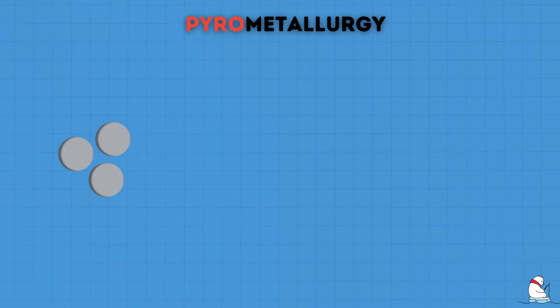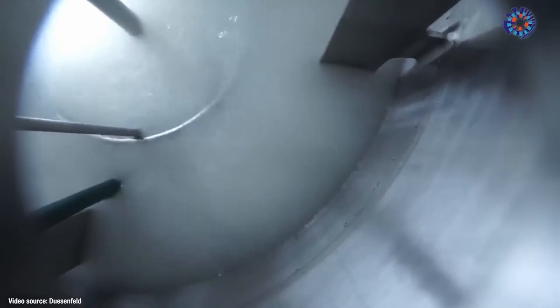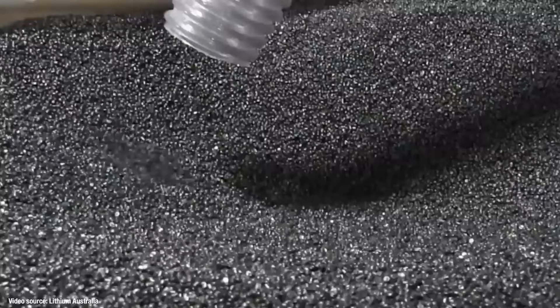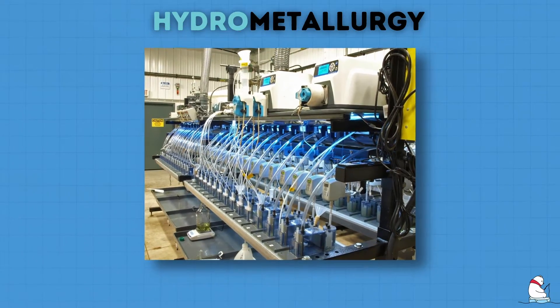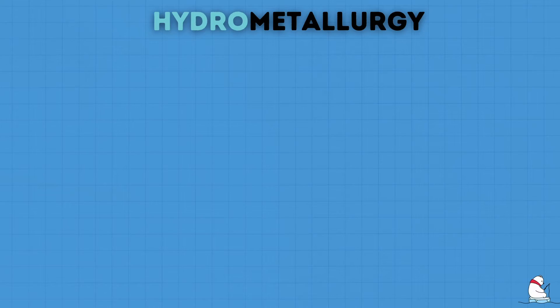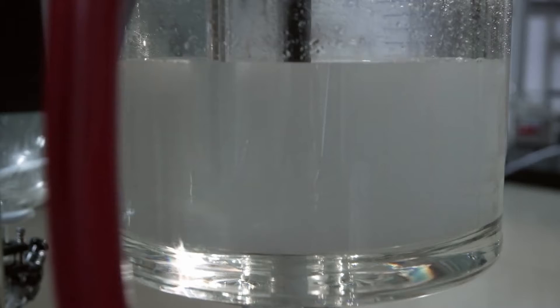The alloy with the other more valuable metals then goes through a hydrometallurgical process. This includes acid leaching and multi-step precipitation to get battery-grade salts of cobalt and nickel. These metals tend to be the focus due to their higher price and thus value. The other commonly used process is just using hydrometallurgy, which uses leaching to dissolve the cathodes into metal ions. More chemical processes are used to extract the metals here, but similar steps — acid leaching and multi-step precipitation — are also used. An important point is that not all hydrometallurgical processes are the same, and they tend to vary between different companies.